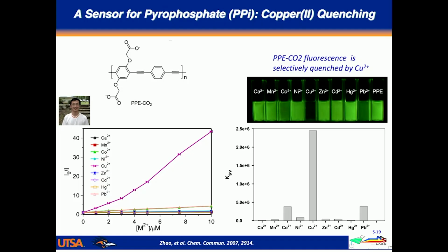So it's this static quenching idea that's enhanced again because the polyelectrolyte is very efficiently quenched once the quencher is nearby it. So that's quite interesting, but it gives us some insight into what's driving this effect, and that is the binding of the metal to the carboxylate.